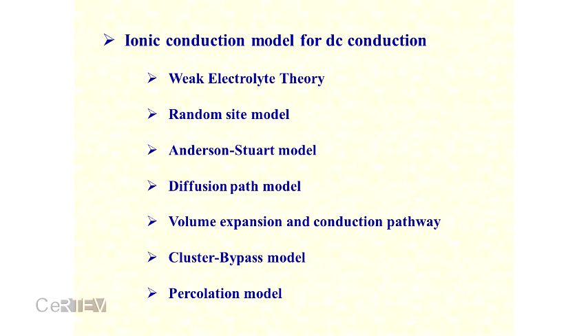In the weak electrolyte model, the mobility is not changing, but the concentration is changing with temperature. And in the strong electrolyte model, the concentration is not changing, but the mobility is changing, because we assume that all ions are taking part in the conduction process. So there is no change in the concentration of the ions as a function of temperature, because there are no more ions to take part in this process.